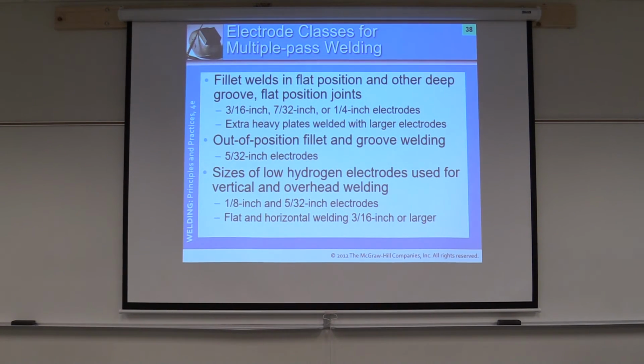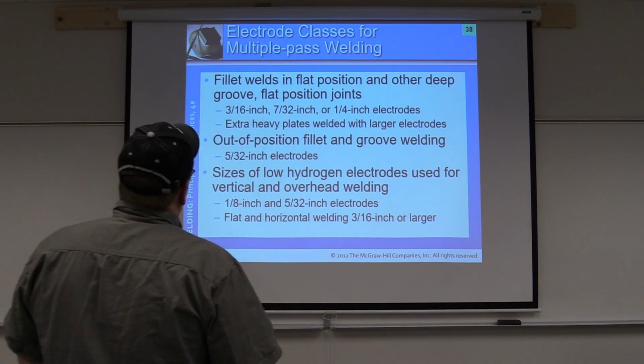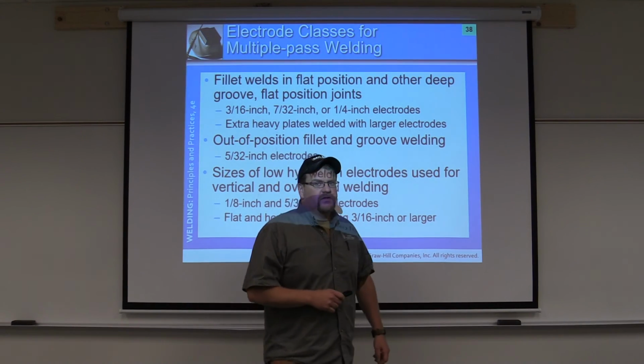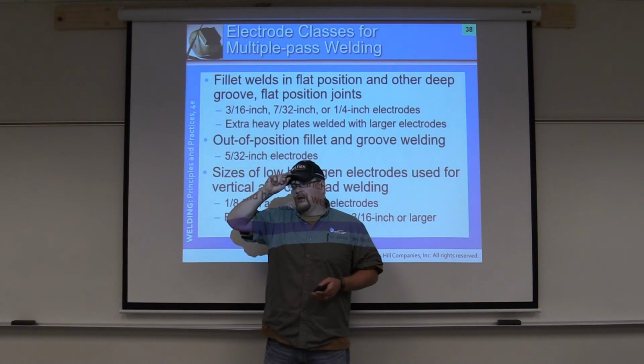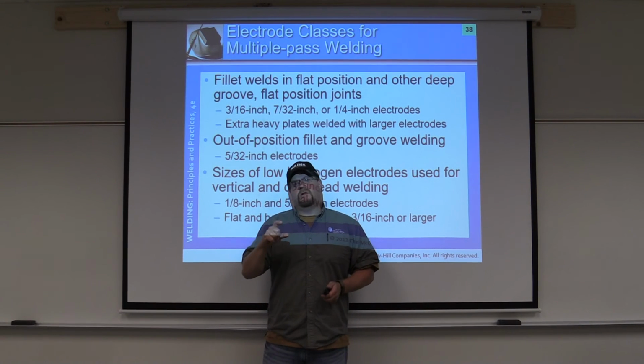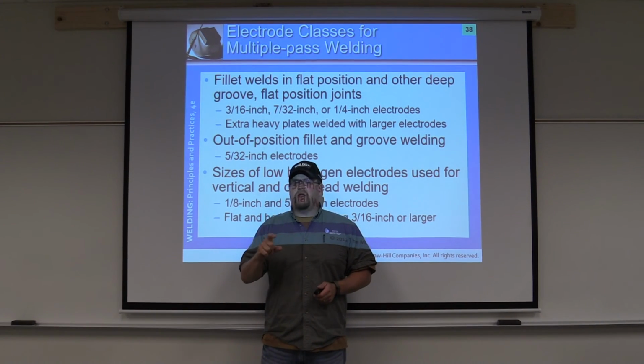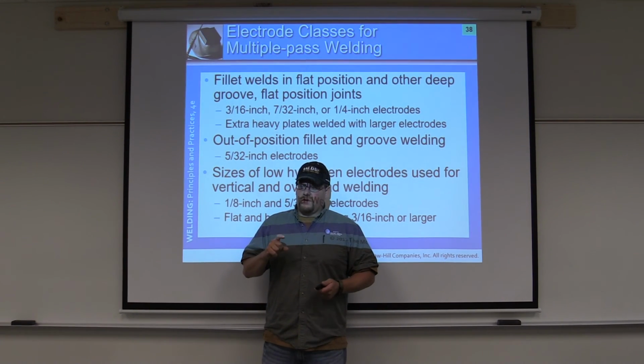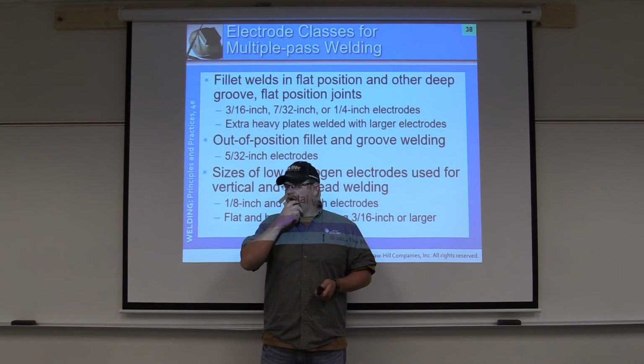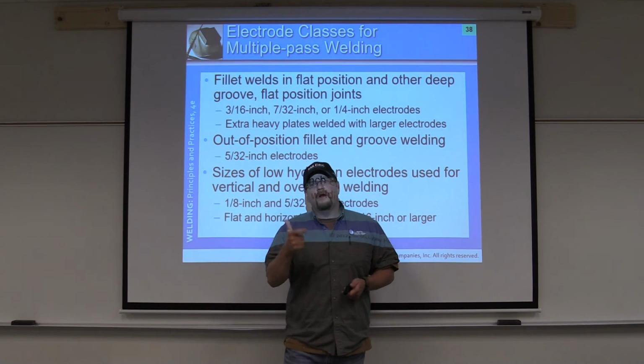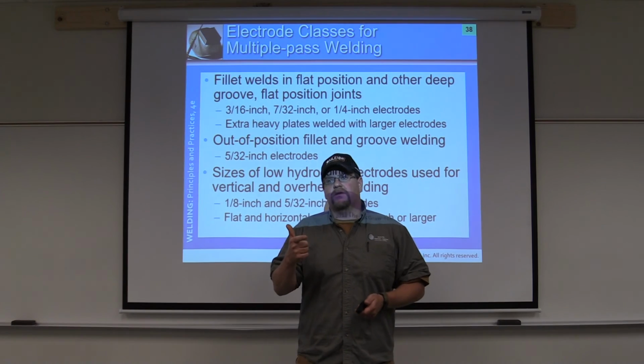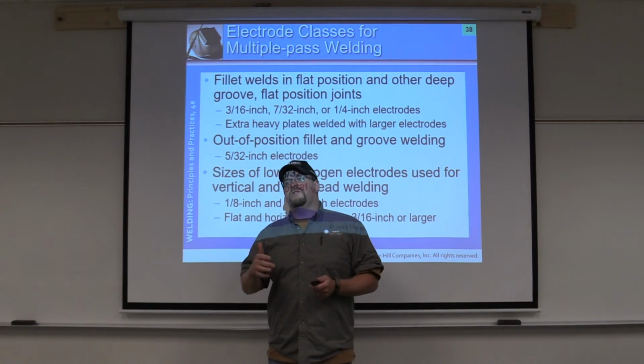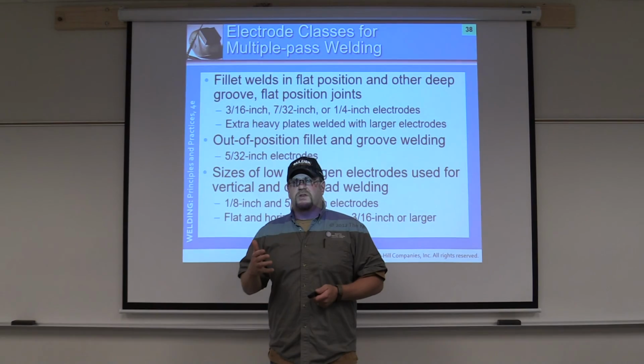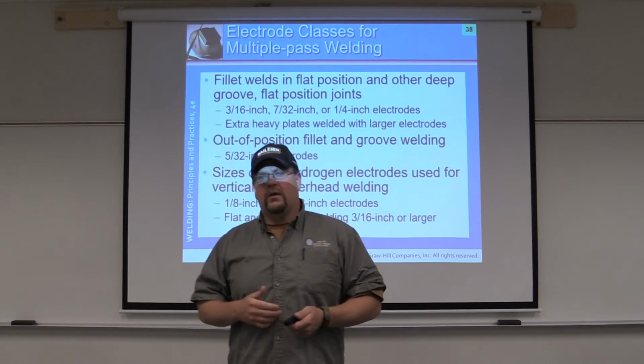By the time you get to a 1/4 inch electrode, you're running 260, 270 amps. We used to run that, that's shipbuilding. Let's say 1-2 inch material, and that's a tremendous amount of heat input into that. So the distortion alone is pretty incredible. When you're welding with a 1/4 inch electrode, usually you're making sure that you're preheating and you're maintaining a 300 to 400 degree preheat to start with. It's keeping the molecules out there so you're not shocking the molecules in the system and putting stress and strain on the grain structure. Okay?